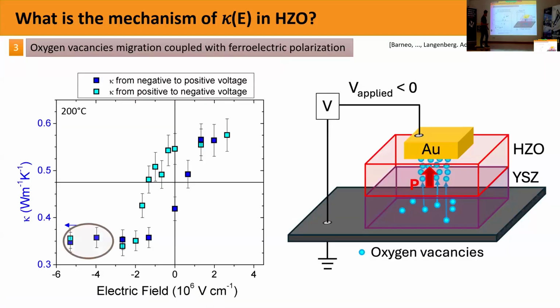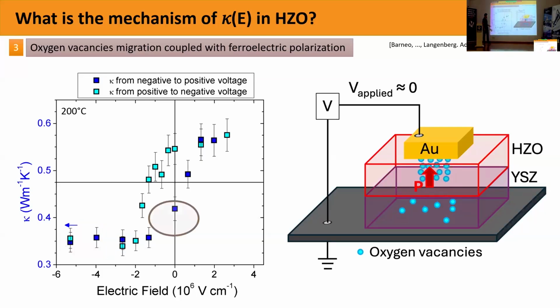Then our theory is that we are dragging and depleting oxygen vacancies with the electric field. When we apply a sufficiently large negative electric field from the top gold electrode, we are dragging the oxygen vacancies of the YSZ into the hafnium zirconium oxide, and these oxygen vacancies are going to scatter phonons. We're going to reduce the thermal conductivity, and that's why we have this low thermal conductivity here. Then, if we go to 0, because we have polarized our hafnium zirconium oxide this way, this polarization inhibits the oxygen vacancies from coming back to the YSZ. So the oxygen vacancies basically stay there, even though the electric field is 0. That's why we have this non-volatility of the state.